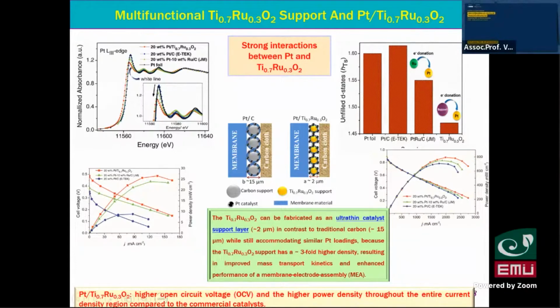Besides some novel properties, we found a strong interaction between Pt and our support, and very stable titanium in the fuel cell environment. But we found that titanium ruthenate oxide has high density compared to carbon. Carbon has very low density, meaning that for the same mass, like one gram, we need to use a lot of carbon.